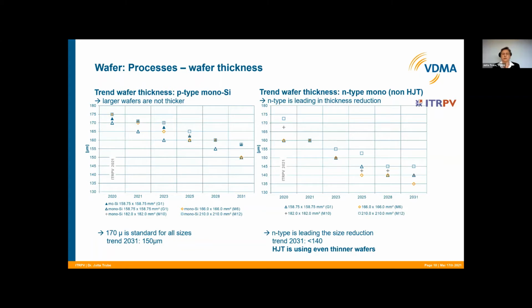Also, the silicon wafer thickness is decreasing, as we heard before. For the P-type mono, this is at the moment, as we just heard, between 170 and maybe slightly less for the smaller ones, and will drop down to about 150 micrometers in 10 years. The N-type material is already thinner, so there we have, in 10 years, less than 140 micrometers. And the heterojunction is even thinner in the wafers, because this time we only asked for the size, not for the technology. This is the reason why the median value is not focused on the very thin heterojunction.